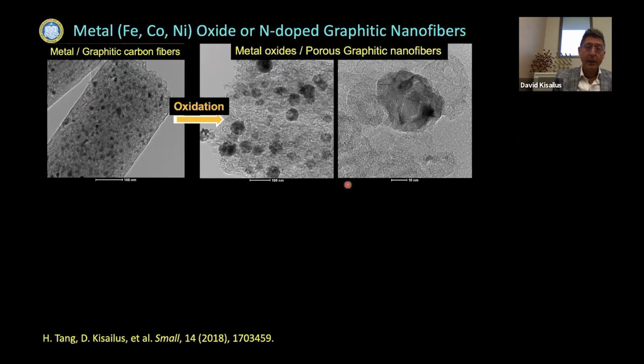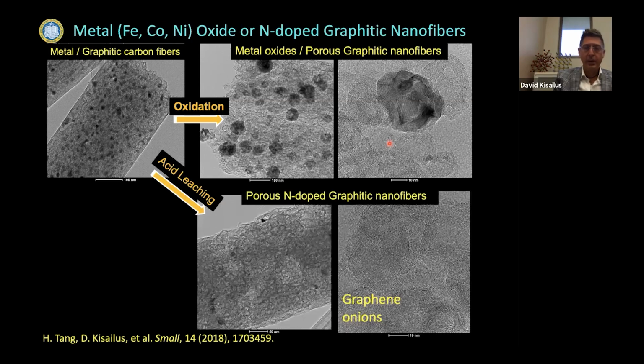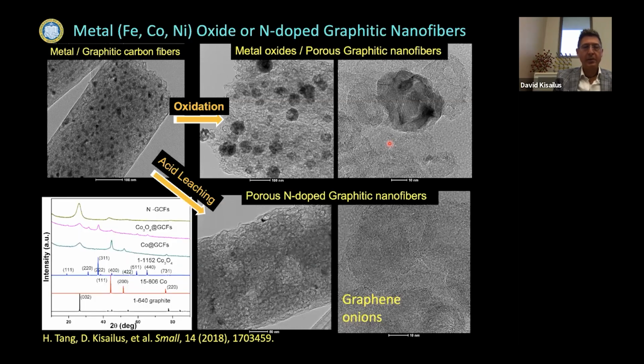But it's formed a metal graphitic type of composite material. We can subsequently oxidize the metal at a low enough temperature where the oxidation will occur. We can also keep the graphene in place, but we can burn out the disordered carbon. So now we have porous metal oxide, graphitic composite fibers. We can also remove the metal if we want, or metal oxide.